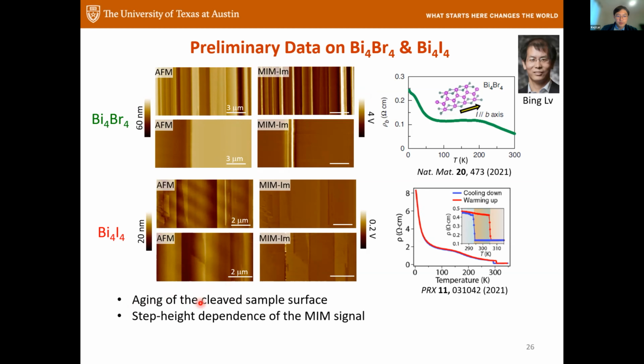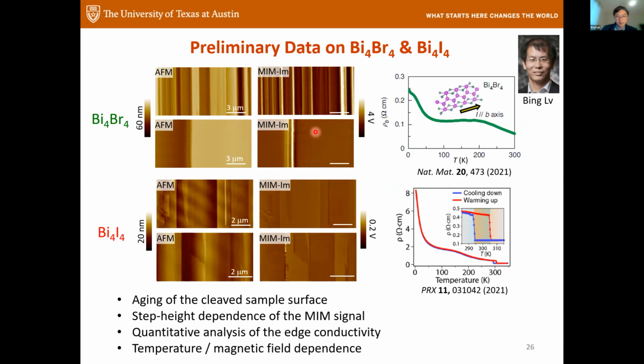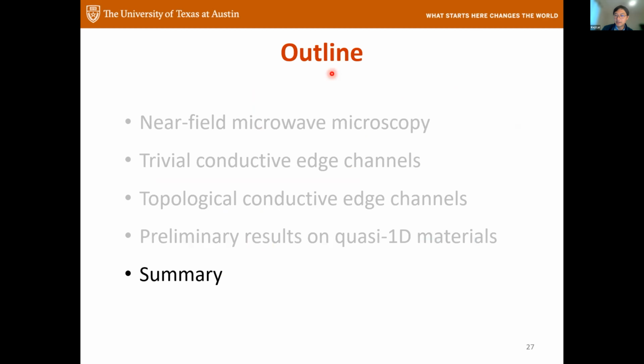The second step is we want to do a systematic step height dependence, like zooming into these small steps and see whether we see any dependence of the signal strength as a function of the height. And we also hear that even for the same height, the left edge and the right edge could be different. Right? Again, from Shafayat's nice talk yesterday. And after this, we will do some quantitative analysis and see if this large signal makes sense. And after that, we're going to cool the sample down and use magnetic fields to really find out whether they are topological or not.